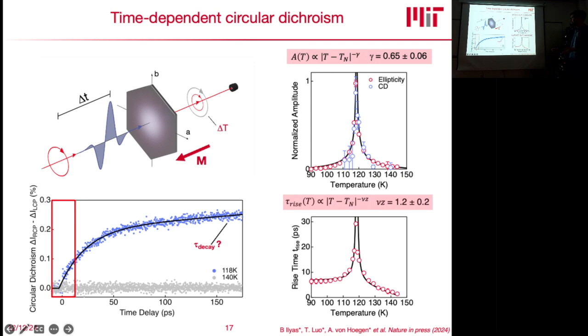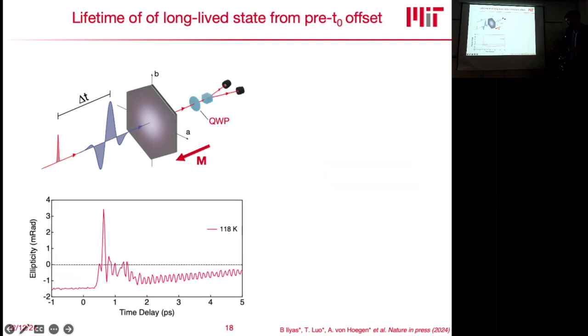Now the question is, how long does it live? With our delay stage, so the delay between pump and probe, we're limited to 150 picoseconds. We can't probe any further out. And it seems like it's still rising after 150 picoseconds. But what we can do is look into before time zero. If you see a before time zero signal, as we do, it means that the dynamics that you launched haven't had time to relax back to the initial state between two separate laser pulses, since this is a pulsed experiment where the pulses are separated by 1 millisecond.